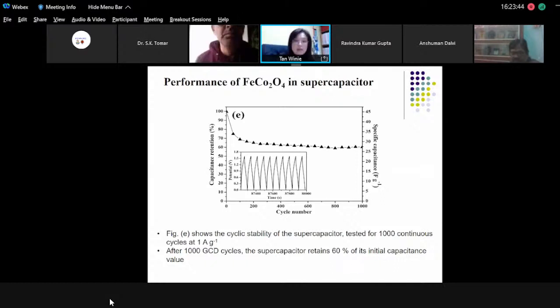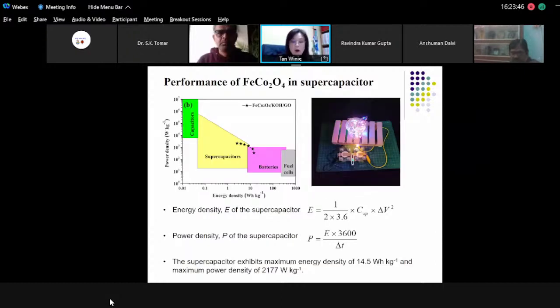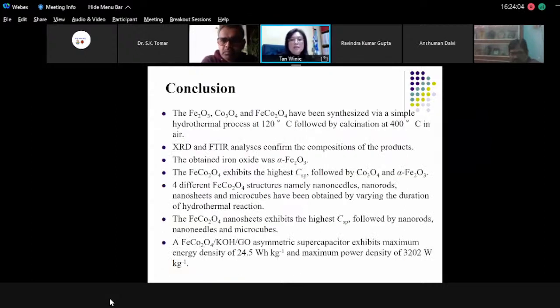We also calculate the energy and power density of the supercapacitor. The maximum energy density is about 14.5 watt-hour per kg, and the maximum power density is about 2,100 watt per kg. So this is the conclusion that I'm not going to read.